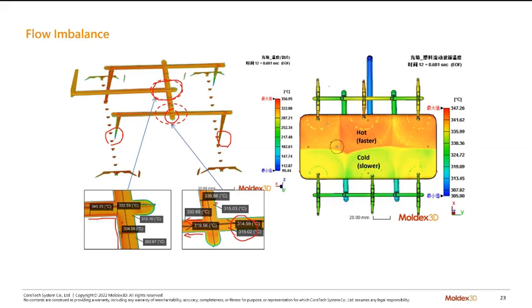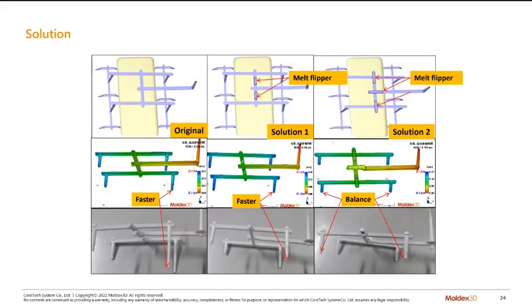And if we check the melt front temperatures in this part, you can see that the temperature is very interesting. One side is hotter than the other side, and this is caused by the shear heating issues. So now they find out that the problem is caused by the shear heating, so they use these melt flipper features or geometries to try to remove the uneven temperature issues.